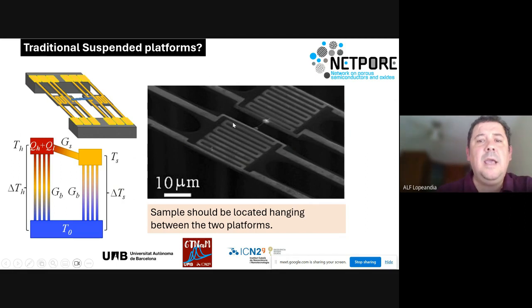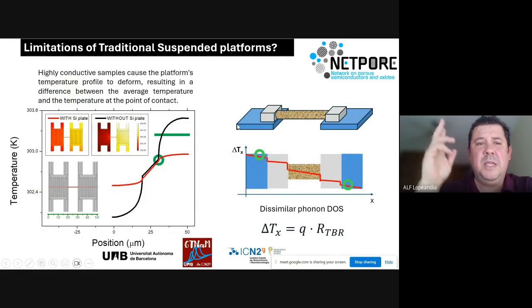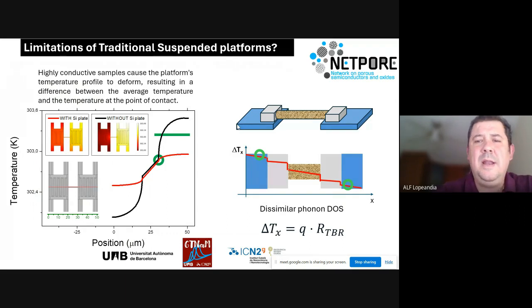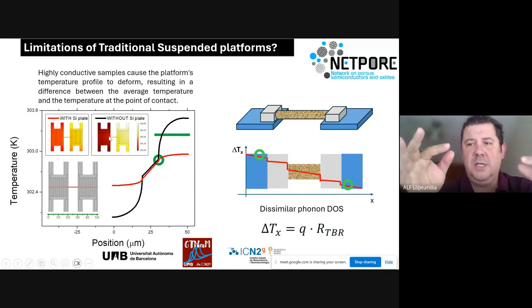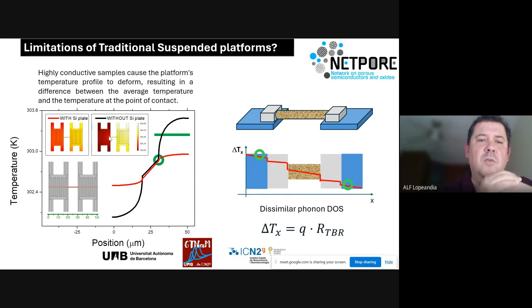That technique has a limitation that we wanted to overcome. In fact, it has two limitations. I said one, but it has two. One is that if we have a highly conductive sample, as you can see here in the picture, and we attach the nanowire to the two borders of the platforms, and we measure the temperature profile within the 20 square microns of the platform, here is a finite element model of the temperature profile. If we take a cross section, a temperature along this line, we will measure the temperature in the platform, in the wire, and in the other platform.